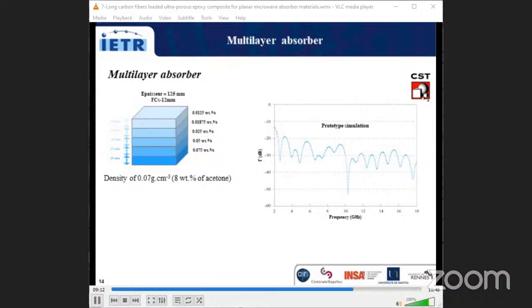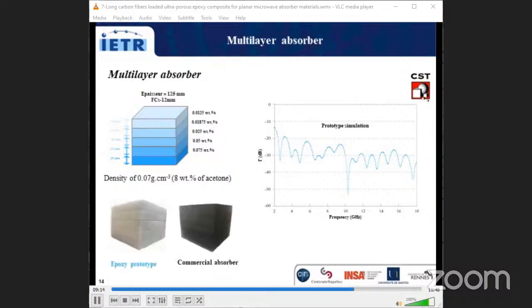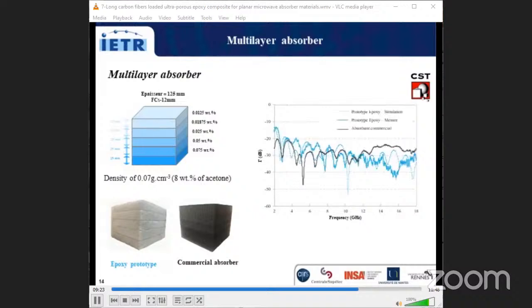The multi-layer prototype is carried out with these 5 layers, and the measurement of this prototype is done and compared to the simulation and the measurement of commercial absorber. First, we can notice that the measurement of the realized prototype shows a reflection coefficient curve quite similar to the simulated one. Moreover, the absorption performance of our prototype is very close to the performance of the commercial material and slightly better at some frequencies, especially at high frequencies.